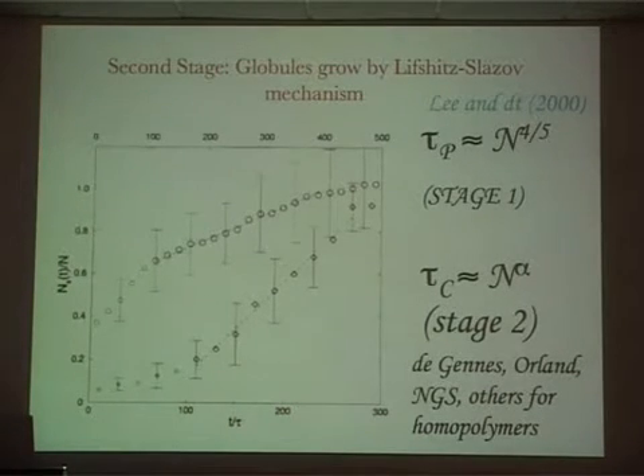It is topologically constrained, but you still form these big clusters that engulf the small clusters. But it seems to be happening by a phase separation type of route rather than nucleation. I'm just talking about the monomers only, not the solvent. But you're right that because I cannot cut the chain, there is some tension between the two clusters, and then they coalesce. It's technically maybe still non-nucleation.